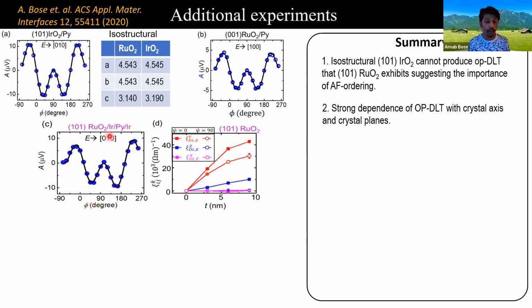Okay, so we also measured spin orbit torques in other planes of ruthenium dioxide, for example, 001. In the 001 plane, we also don't observe any extraordinary spin torques or spin currents, which is in agreement with the theory. That means, again, there is a strong crystal axis dependent extraordinary spin orbit torque, not only crystal axis, but also crystal planes. The third thing is we inserted a spacer between the source and the detector.